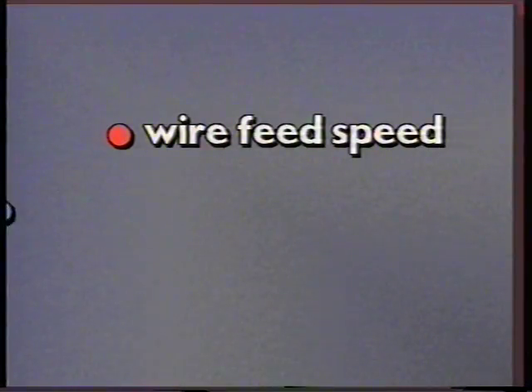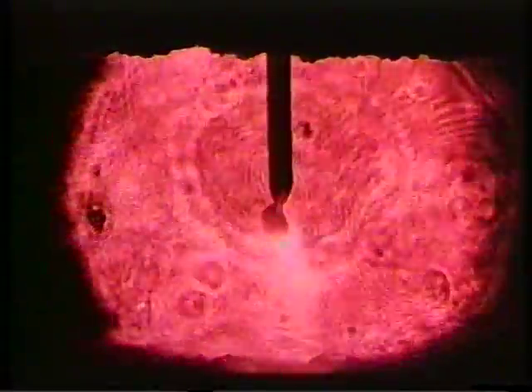The main controls to the gas metal arc welding process are the wire feed speed, the arc voltage, and the inductance. The wire feed must match the rate at which the filler wire is melted, and this is related to the weld current. If the arc voltage is set too high or the wire feed speed is too low, then the arc length will become too great and the wire may burn back into the contact tip. If the voltage is too low or the wire feed speed too high, then the filler wire does not melt correctly and short-circuits the arc gap, causing an effect known as stubbing.